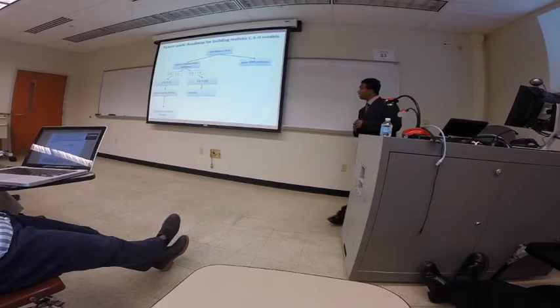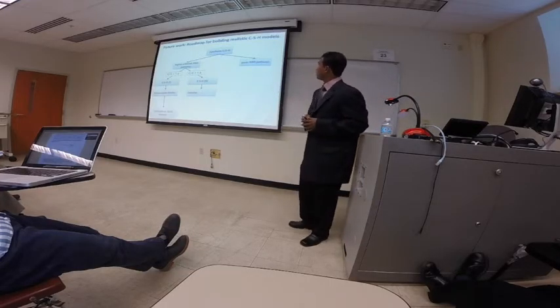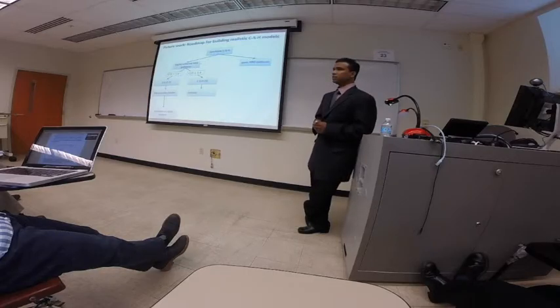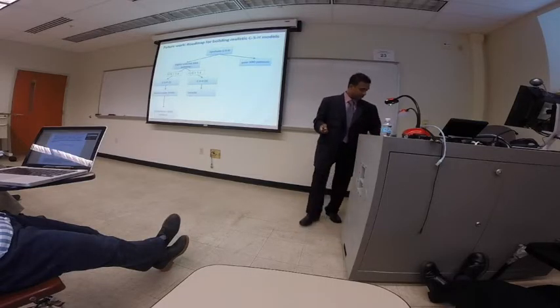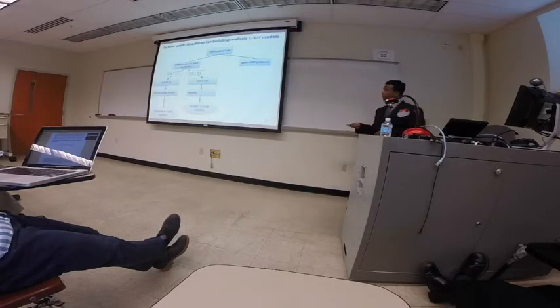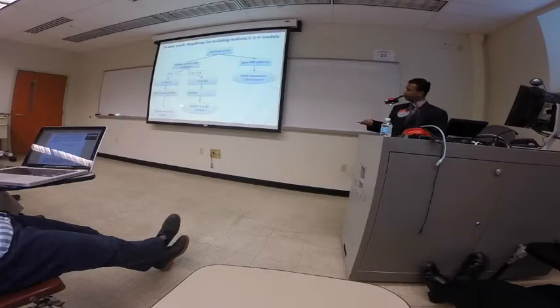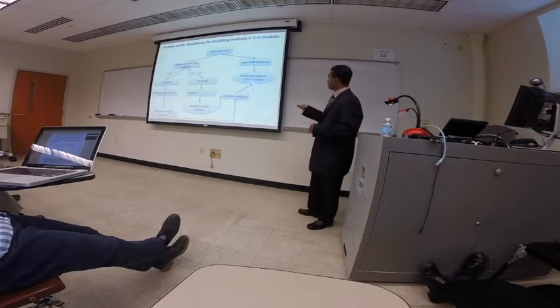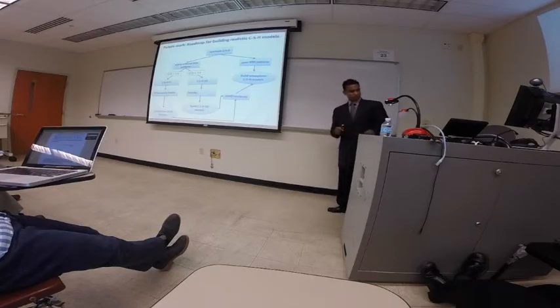Now to give a roadmap to building a realistic CSH model, this is my hypothesis: we already have Richardson models for CSH1 type of cement. Then a similar argument can be made, and we can build CSH2 type of models. But what we really want is an amorphous model. So to build an amorphous model, we could use these two models as seed models and use ab initio molecular dynamics techniques to build an amorphous CSH model.